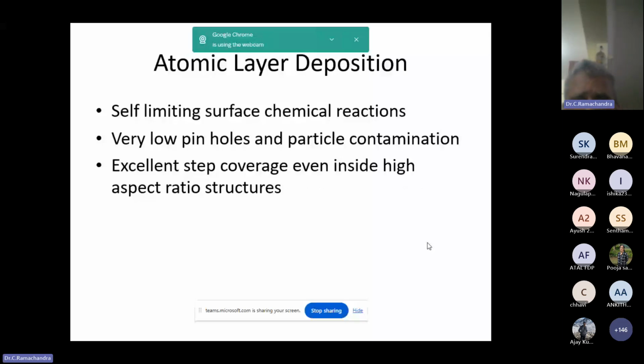Then, as I said, the ultimate in thin film deposition, as far as thickness control is concerned, is atomic layer deposition. What is atomic layer deposition? Only one atomic layer. So there is no question of thickness variation. It is 100% uniform because I am depositing only one atomic layer. If you say 1 micron thickness, it will have several thousands of layers. Here only one layer is deposited in one cycle. If I want a second layer, I have to go for a second cycle. If I want a third layer, I have to go for a third cycle.